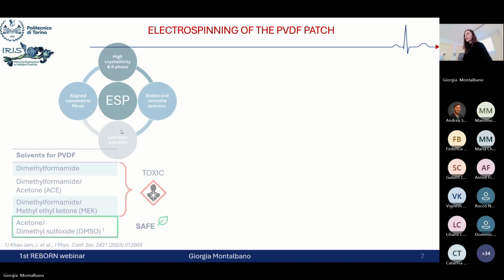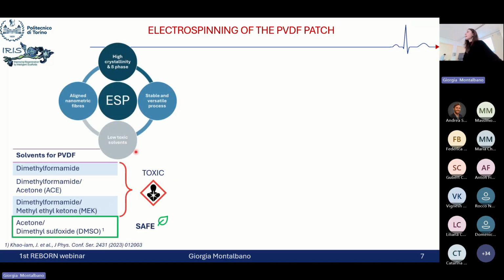biomimetic constructs. So starting from the material formulation, as you know, despite the great advantages represented by this technique, one of the main limitations is represented by the large use of very toxic solvents that are very effective in the processing of the polymeric formulation, but can be harmful, of course, not only for us but also for the environment. So one of the goals in our project was to replace the use of these toxic solvents with some less toxic mixture. And so in this case, we decided to select a mixture of acetone and DMSO in order to replace the most commonly used dimethylformamide, normally used for the processing of PVDF.